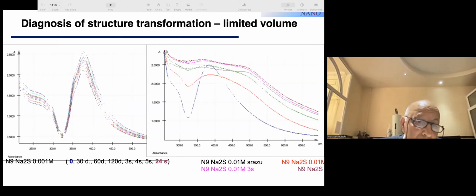for concentration 0.001 mole, but on the right side we showed the modification of silver nanowires in sodium sulfide solution with concentration of 0.01 mole. We can see that in limited volume,